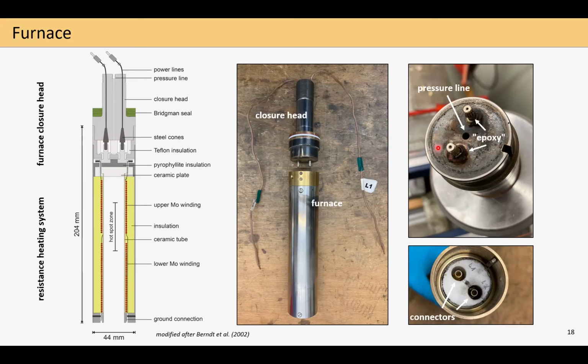And although this looks not very happy anymore, I would say, so relatively burnt, I'm still astonished that such a looking closure head, well, this happens after a few experiments, and then maintains for half a year or so, still pressures of up to 500 megapascal. And this would then just be the interior of the furnace here on top. So the connectors here to these two steel cones, so for the electricity.